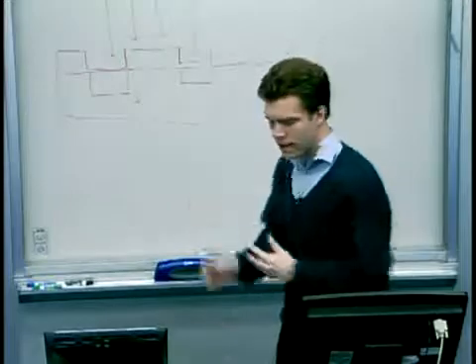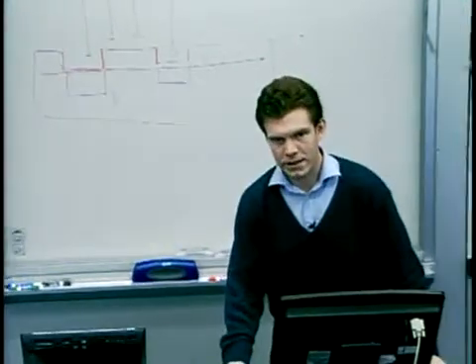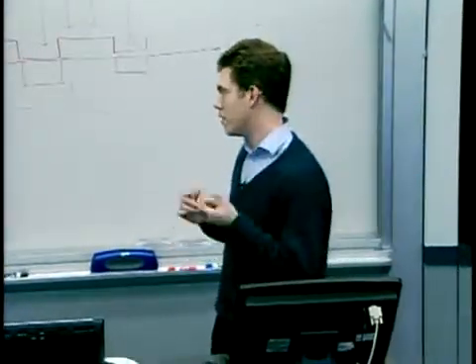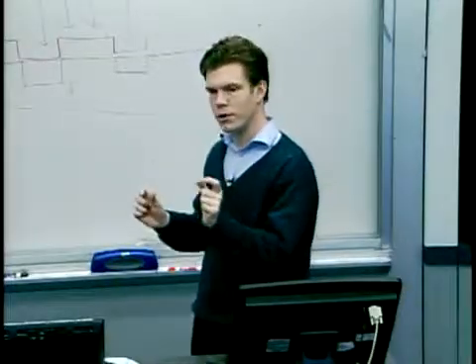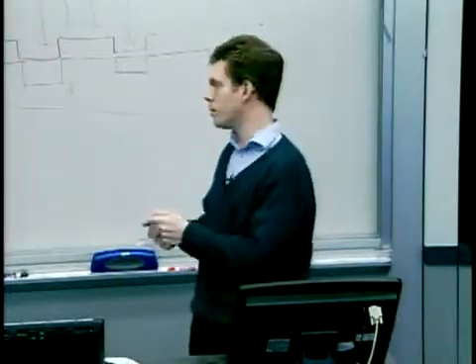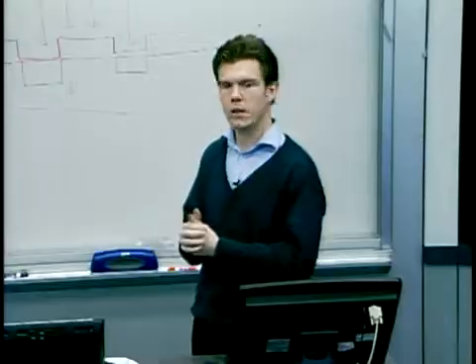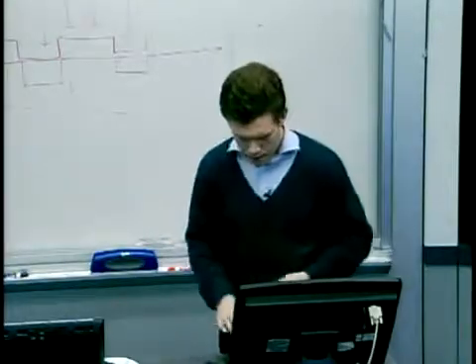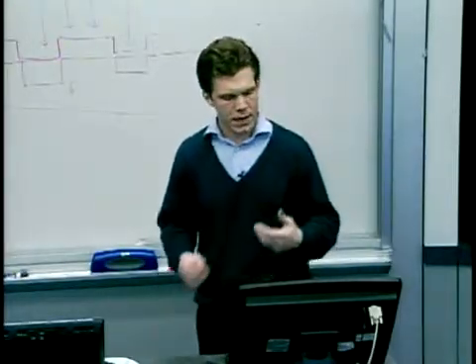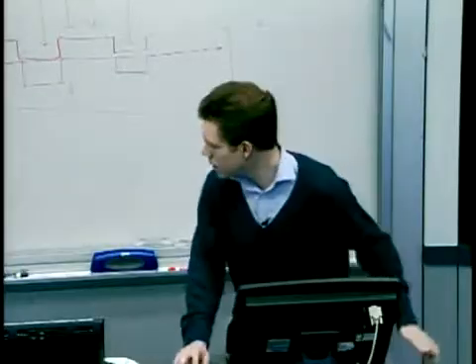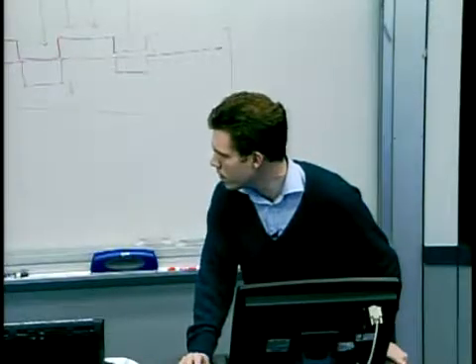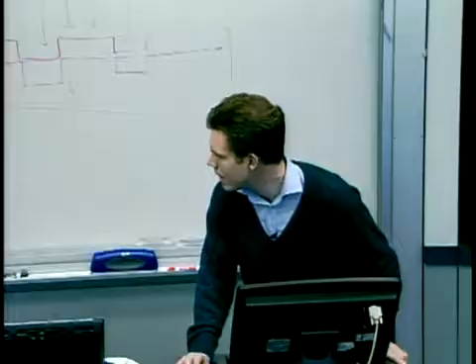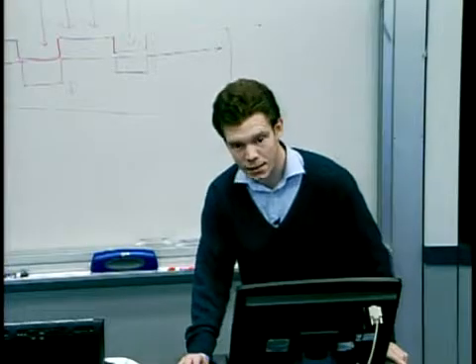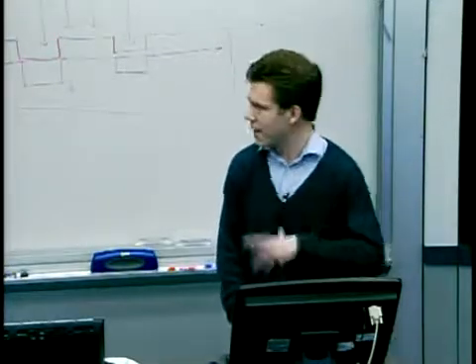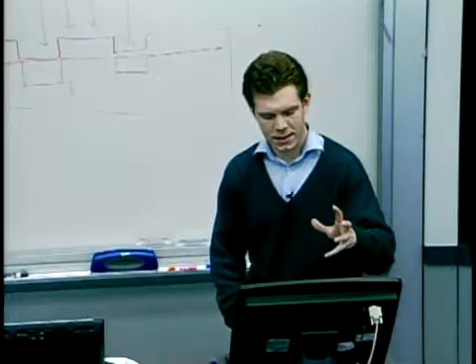Finally, we've got, at the smallest scale, effects to do with individual features. So if an individual gap is too small, say, that's going to be very hard to force polymer into it, and that could be a showstopper. So we've got these three different length scales. I've alluded to these sorts of problems: bowing of the platens, non-parallelism of the platens. They relate to the substrate scale effects.